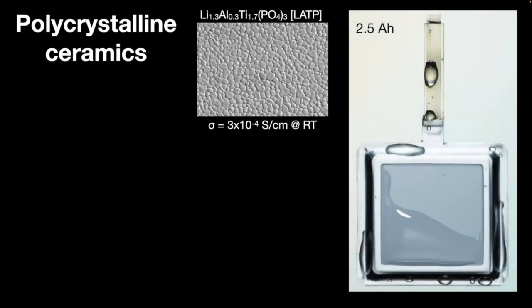Let's focus on polycrystalline ceramics for a second. Why? Because they're certainly interesting, and there's a large world of conductive ceramic materials available to us with good lithium ion conductivity and sodium ion conductivities in some cases. But this particular ceramic, lithium aluminum titanium phosphate, known as LATP, is not only highly conductive at room temperature, but it has the unusual property, and this is the only material we found that has this property, of being exceptionally stable to aqueous environments.